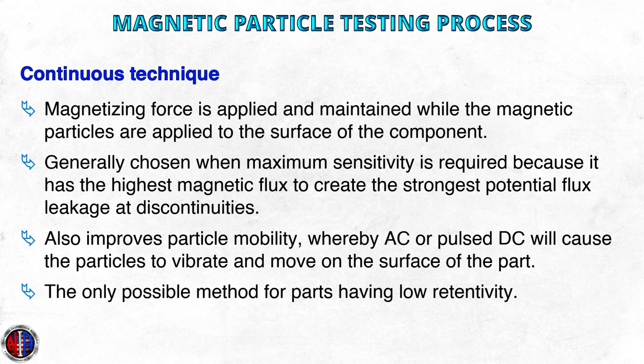In a wet horizontal testing unit, the application of the particles is stopped just before the magnetizing force is applied, but since particles are still flowing over the covering of the surface, this is considered continuous magnetization. The continuous technique is generally chosen when maximum sensitivity is required because it has the highest magnetic flux to create the strongest potential flux leakages at discontinuities. Additionally, the continuous technique is advantageous to improve particle mobility.